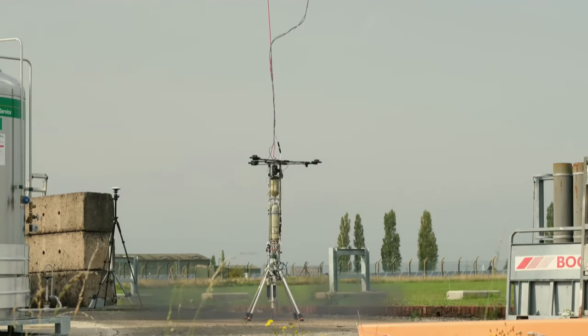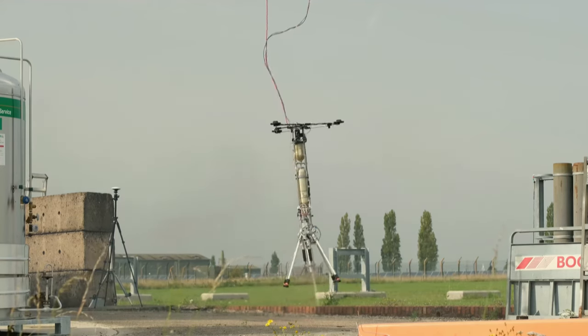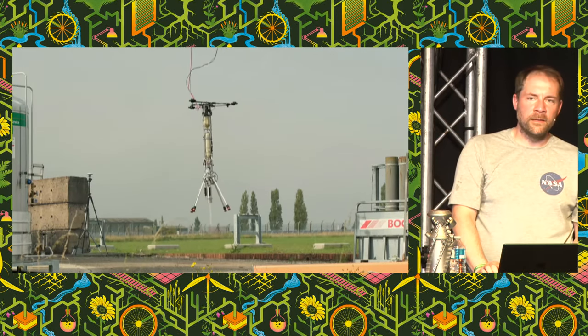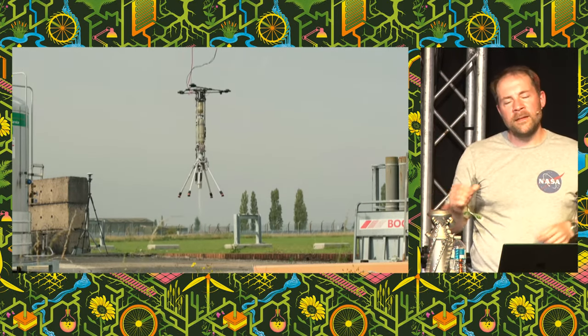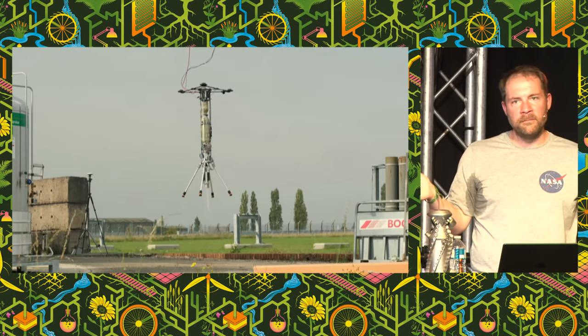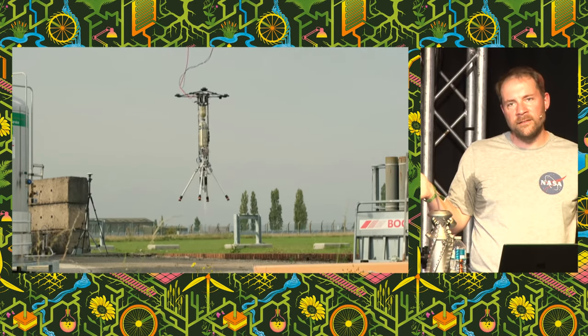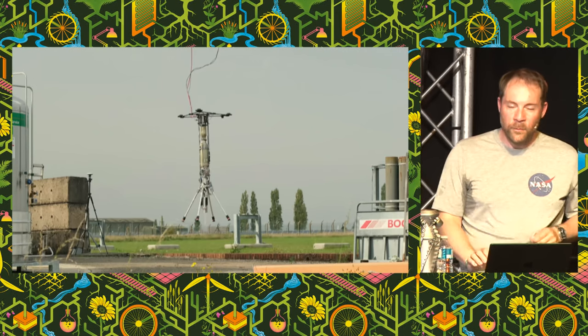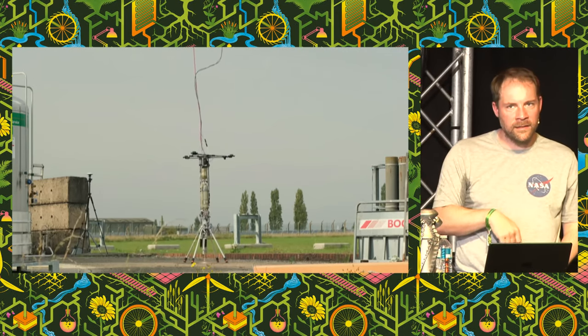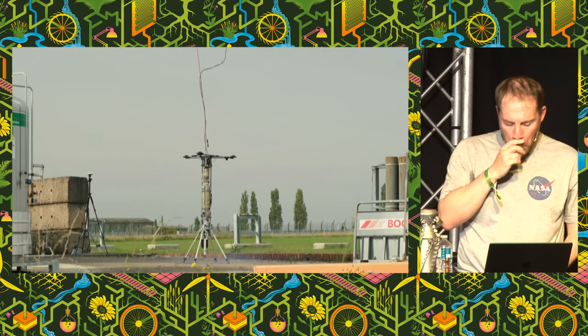And the answer is because conventionally, rockets don't like being fired lots of times. People think that the lifetime of a rocket is defined by how long its burn time is. But actually, if you just turn it on once and leave it for many tens of seconds to minutes, it's often quite happy. What actually kills rockets is the thermal cycling. It's the being turned on and being turned off.